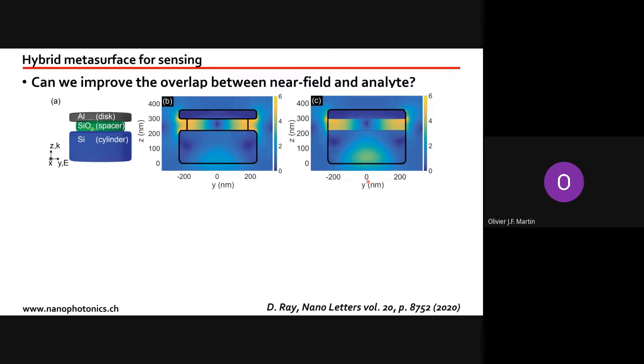You see here our structure with the silicon cylinder, the glass spacer, and the aluminum disc. When we computed the field intensity distribution, it turns out that most of the strong field, so the field which is going to change the response of the system, is inside this dielectric spacer. So we thought, could we actually make this field access the outside world so that it would notice when the outside world, so the liquid surrounding the system, changes its refractive index.